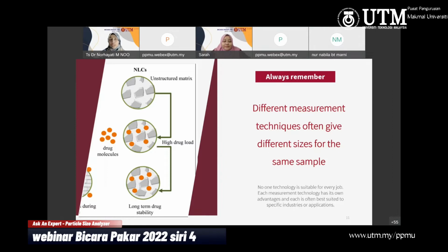For example, if you're working with a formulation with a size larger than the limit, for your information, for this Zetasizer Nano ZP, the size limit from the manual is around 8 to 10 micrometer. But if you ask me, I would suggest that if it is more than 1 micron, please use another technique. I would suggest laser diffraction, which is very suitable for samples of bigger size. But if you have less than 1,000 nanometer, DLS is a really good option, because it gives you results very quickly and easily.